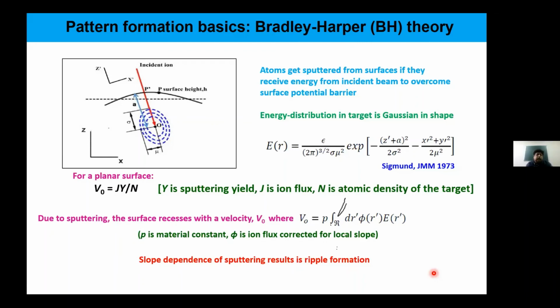And for a planar surface, if we consider that Y is the sputtering yield, J is the ion flux, and N is the atomic density of the target, then the velocity can be expressed in terms of this small equation. And what is this velocity? Due to sputtering, the surface recedes with this velocity.